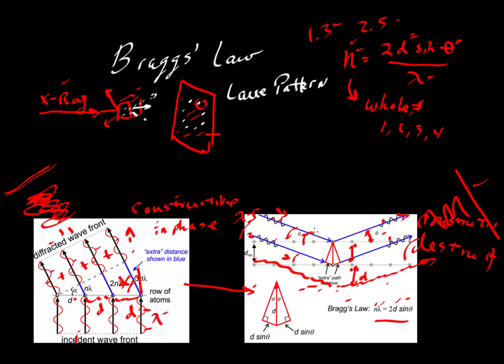But before we go, I want to show one other application. We show the atom here as this gray dot, but it's not really a dot. It's a larger atom. The radius of this atom would be this, and the radius of this atom would be this length here. If we have a pure substance, let's say pure iron or pure gold or pure anything in the periodic chart that we can crystallize, then you'll notice that the distance d here would now be equal to 2 times r, 2 times the radius. So one of the neat things that we get out of doing x-ray diffraction is we could figure out the sizes of atoms. In this very simplistic approach, r would be equal to the d spacing divided by 2.